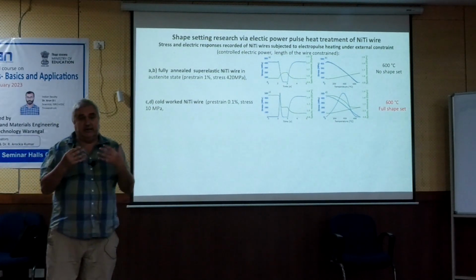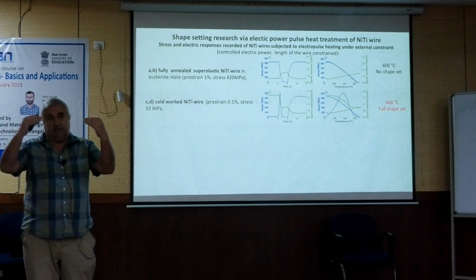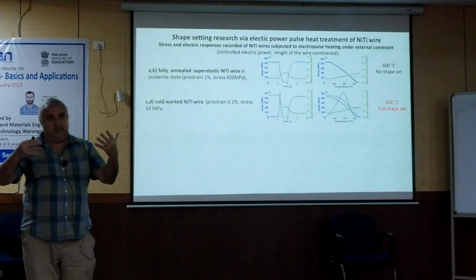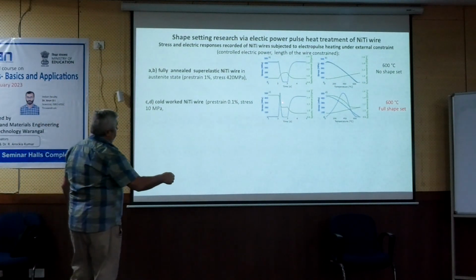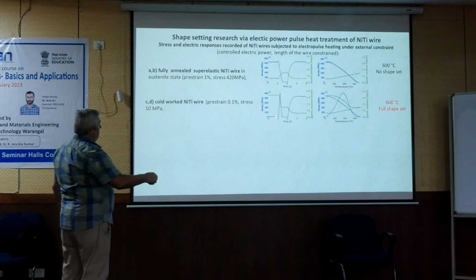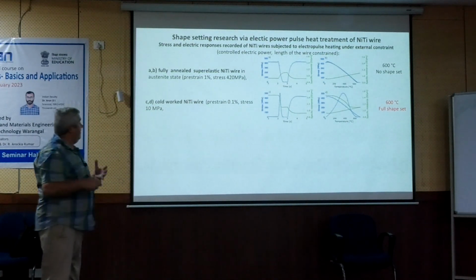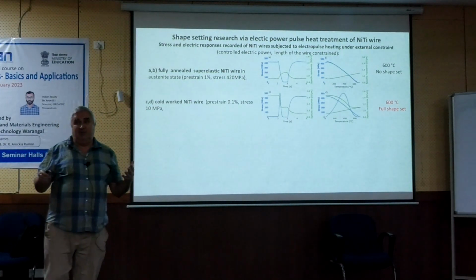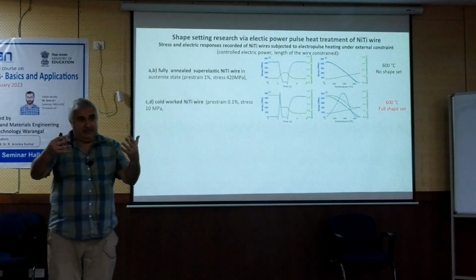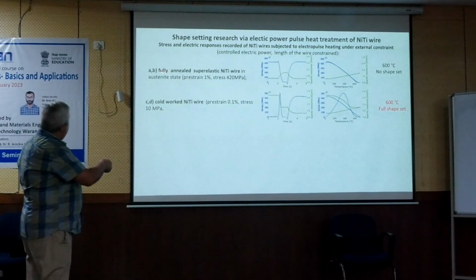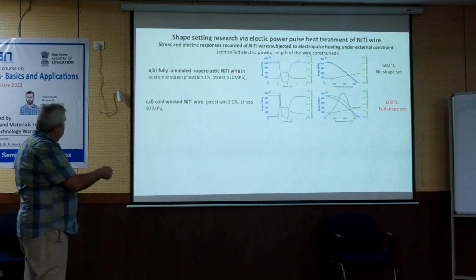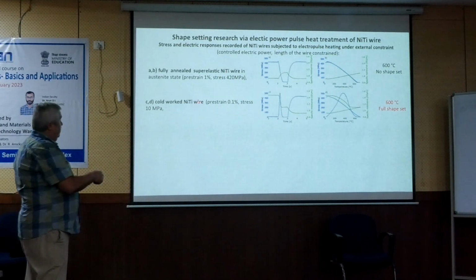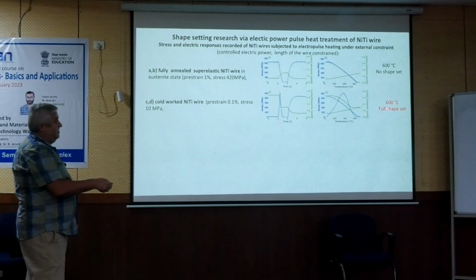It's not annealed, it has inside a lot of defects. And if I heat it to 500, there is recovery and recrystallization. These defects disappear. So the response here is very different. This is the force, instead of going down, the force goes up and down, and the resistance goes down instead of up. And after this treatment, the wire will be perfectly shape set. So now the shape setting is exactly the same, only in the first trial I use austenitic wire which is annealed, which is already super elastic, and this is cold work which is only elastic because of lots of deformation, and the result is different. Here there is no shape set, here there is full shape set.